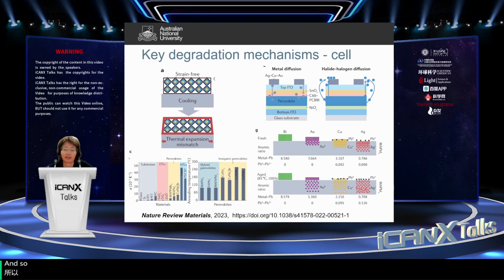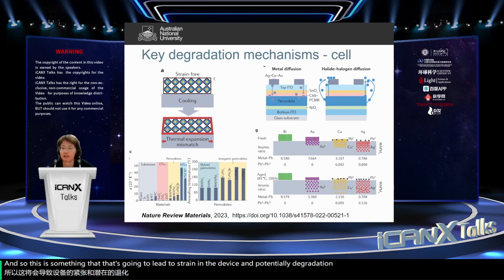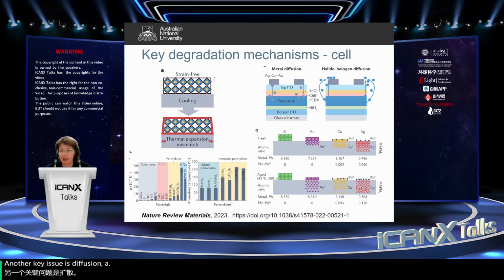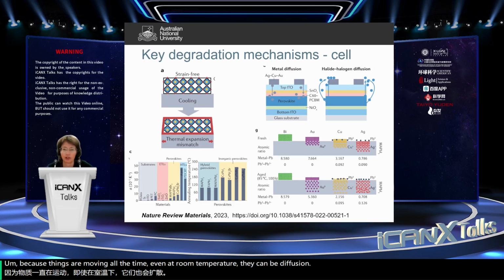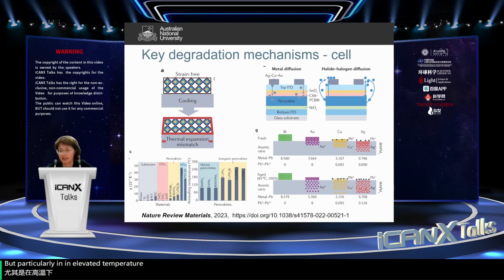And so this is something that's going to lead to strain in the device and potentially degradation. Another key issue is diffusion. So with perovskites, you really have to think of what we're doing here as solid state chemistry, because things are moving all the time. Even at room temperature, there can be diffusion, but particularly in elevated temperatures, such as you might get when you have a solar panel on your roof.